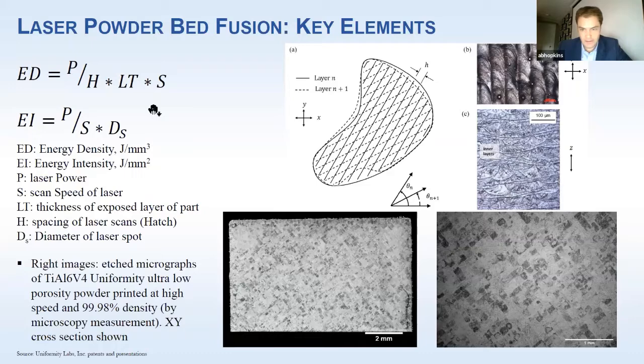And then layer thickness. Layer thickness is the amount the build stage moves at every layer, not the powder stage. That's different from the powder layer thickness, which is usually a few times the actual amount the stage moves. But at the end of the day, your scan tracks are built from a layer thickness perspective, not a powder layer perspective. And then S here is laser speed, how fast you're scanning. That's energy density, in joules per cubic millimeter.